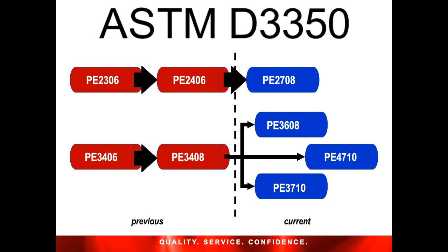This reflects the polymer's crystallinity, which in turn gives the material strength and stiffness. The second digit identifies slow crack growth resistance based on PENT testing, or Pennsylvania notch testing. And third, the last two digits provide the material's maximum recommended hydrostatic design stress for water at 73 degrees Fahrenheit. The PE 2708 material has the last two digits 08, which represents a hydrostatic design stress of 800 psi at 73 degrees Fahrenheit. This is the same hydrostatic design stress as a PE 3408 material, so the pressure ratings are the same.